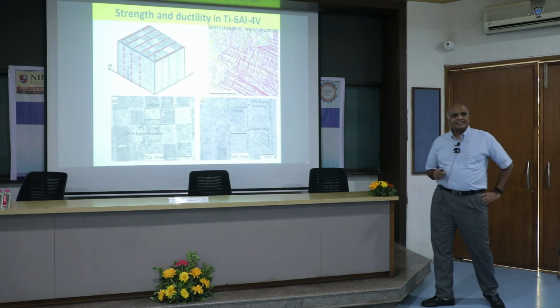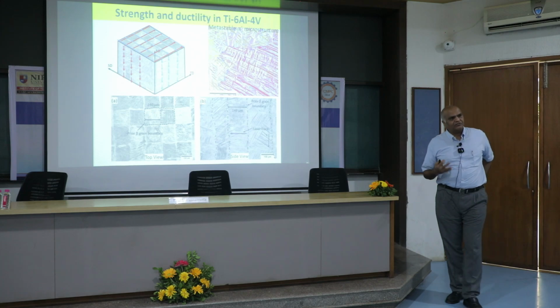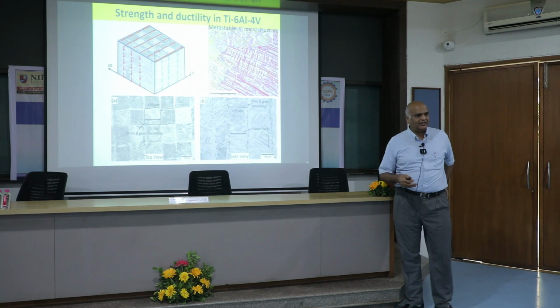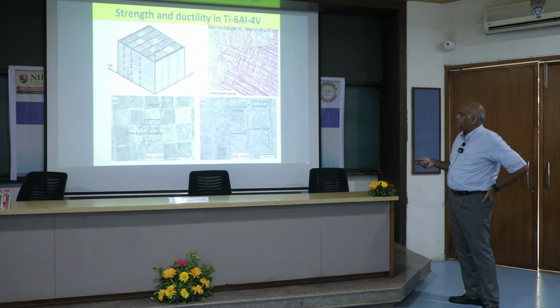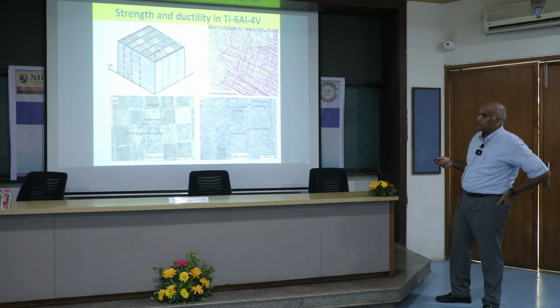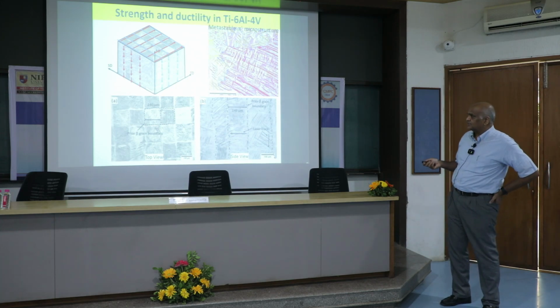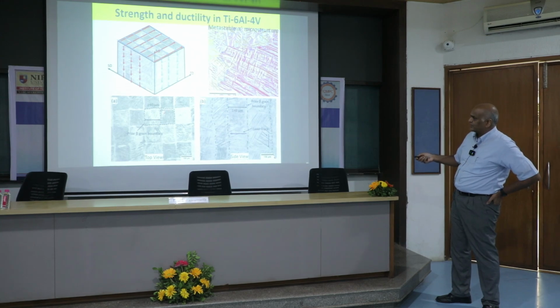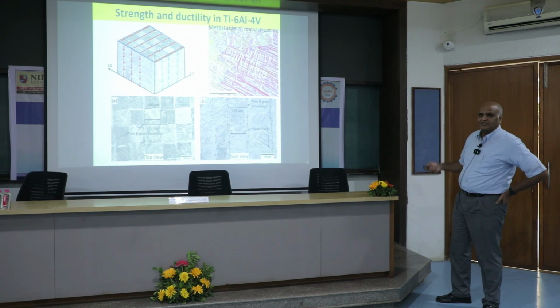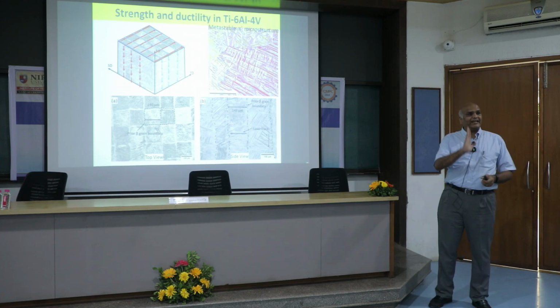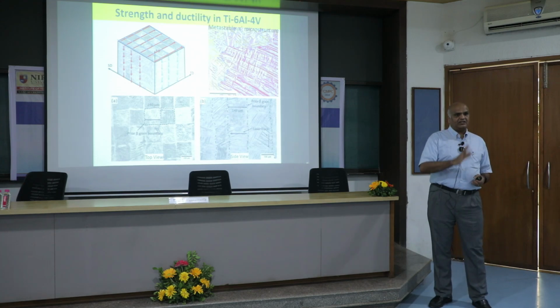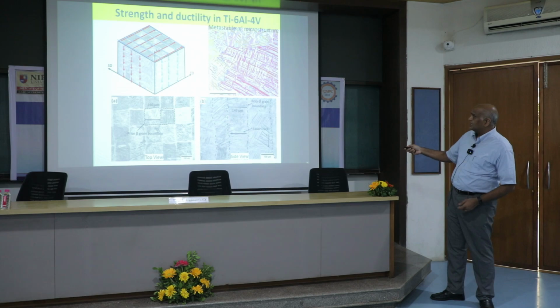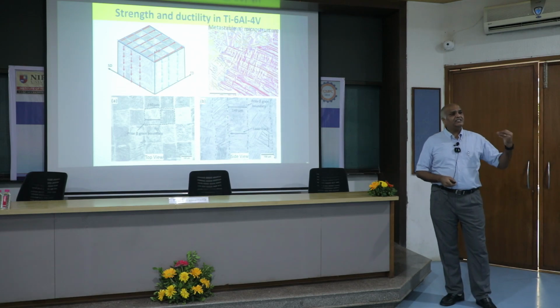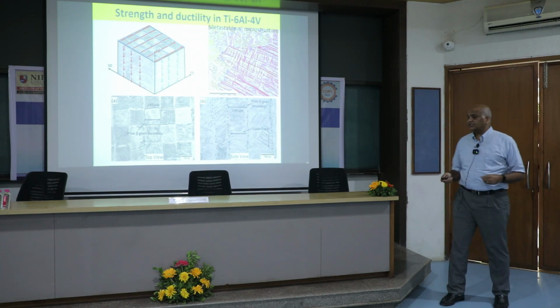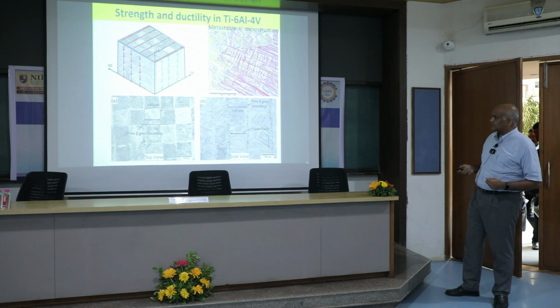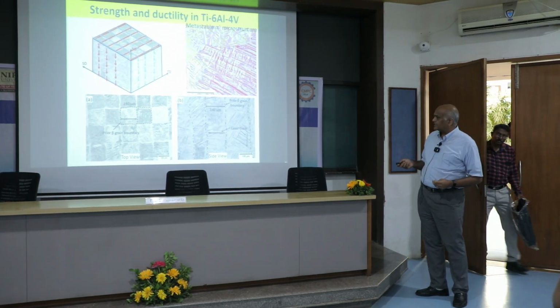Now, let me just focus on Ti-64. This is a very important aerospace grade alloy, right? So what happens is, for example, when you fabricate this alloy with a particular condition, you get square grains on the top, and on the side these are actually columnar grains. There is epitaxial growth that occurs, and as a result you get columnar grains. But remember, the conditions that prevail are rapid solidification conditions, so you get martensitic structures. So these give very high strength to the material.